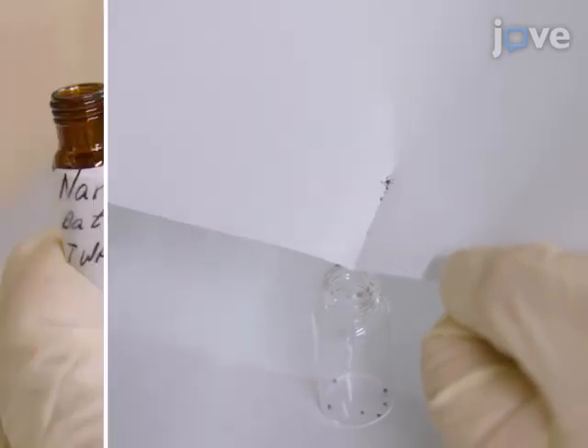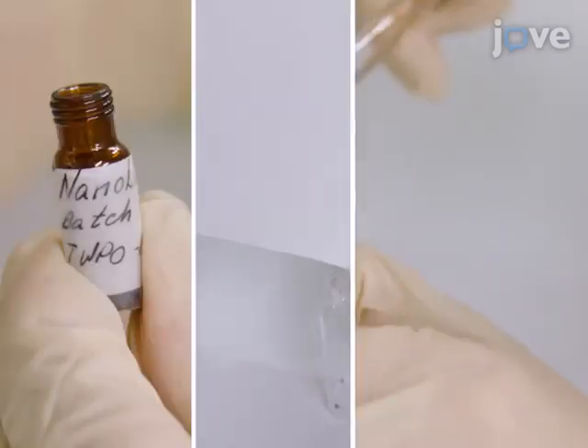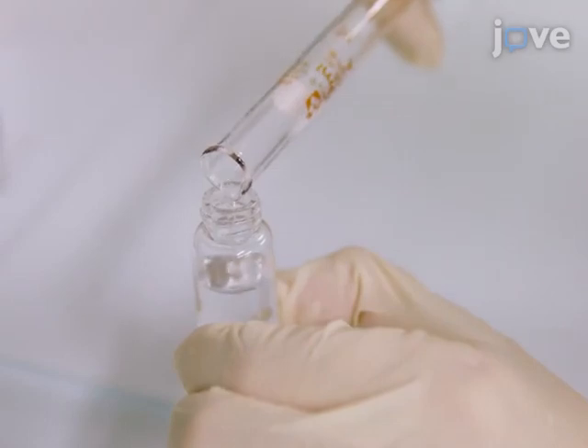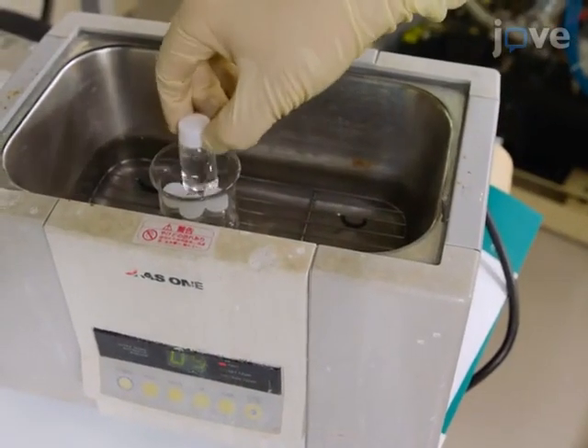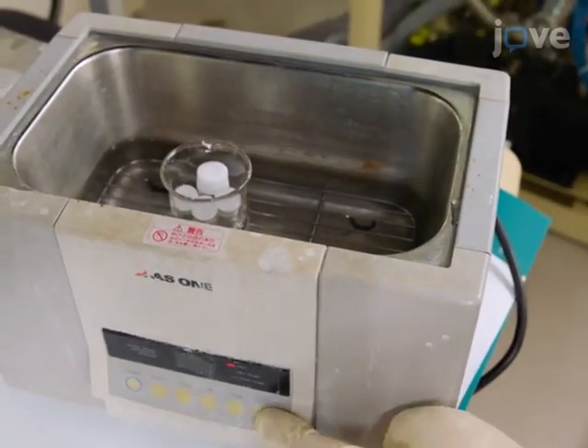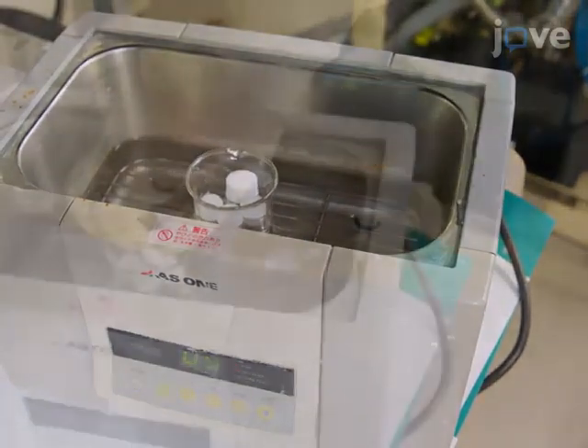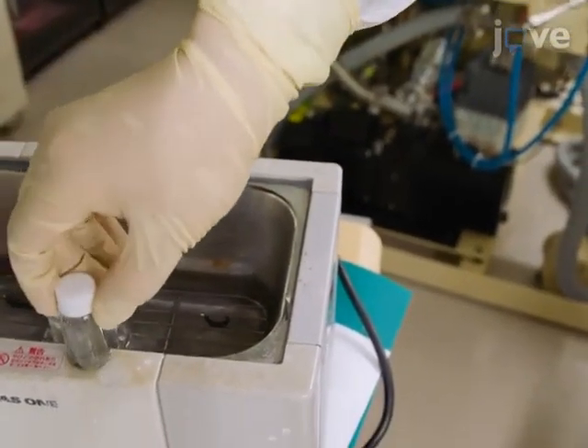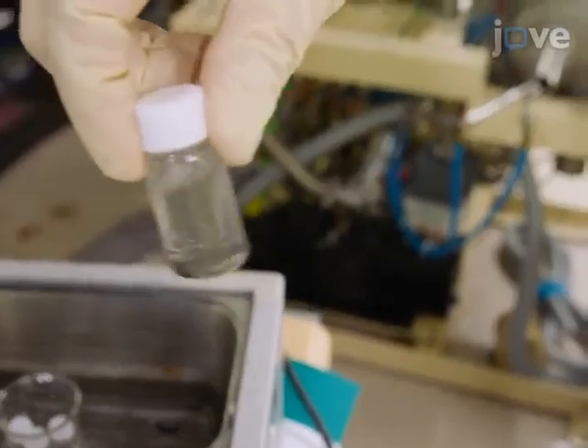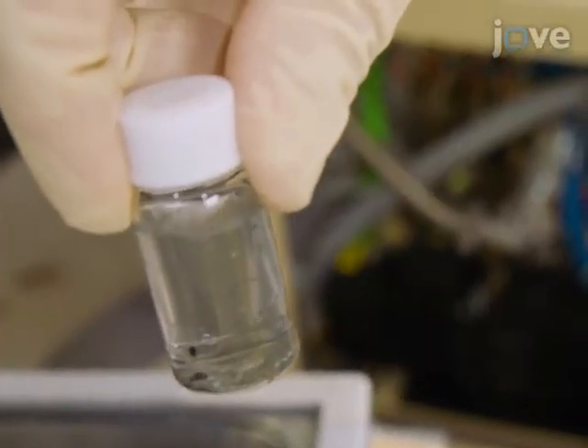To begin preparing the nanotube dispersion, combine about 0.8 milligrams of tungsten disulfide nanotubes with 8 milliliters of isopropyl alcohol. Sonicate the mixture for 20 minutes to disperse the nanotube powder in the isopropyl alcohol. To avoid heating the suspension, rest it for 1 minute after every 5 minutes of sonication.